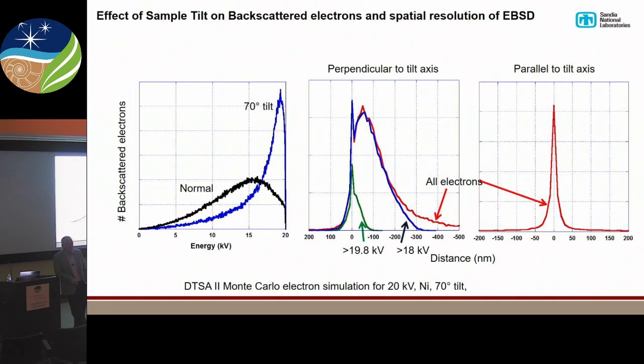Great point, and yeah, you're right. But the thing that we care about are the electrons that come out of the sample that have only lost a few 100 eV of the initial beam energy. And then you ask yourself, where do they come from? They come from an area very close to the beam impact point, because they don't have a chance to go very far and lose energy. And those are the ones that form our diffraction patterns.